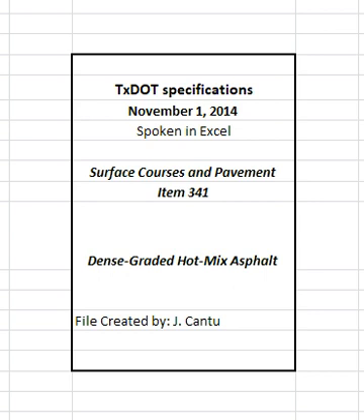4.4.2.1.3 Submitting JMF1. Furnish a mix design report, JMF1, with representative samples of all component materials and request approval to produce the trial batch. Provide approximately 10,000 g of the design mixture if opting to have the department perform the Hamburg wheel test on the laboratory mixture, and request that the department perform the test.